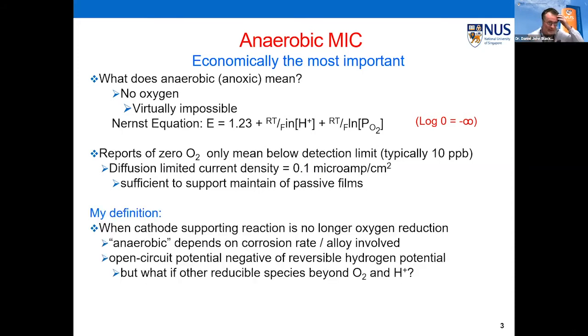So I tried to come up with a better definition for what I mean by anaerobic. And so what I tend to have is when the cathodic supporting reaction is no longer oxygen reduction, it's probably switched to hydrogen evolution. But then of course that means your anaerobic depends on corrosion rate and the alloy involved. So a piece of stainless steel won't be anaerobic and a piece of steel would be anaerobic. So normally I would do it by measuring the open circuit potential relative to the reversible hydrogen electrode. If it's negative of reversible hydrogen, then I would consider it anaerobic. But it's not perfect because what happens if you have other species beyond oxygen and water in there to be reduced? So right at the very beginning, we struggle on terminology.